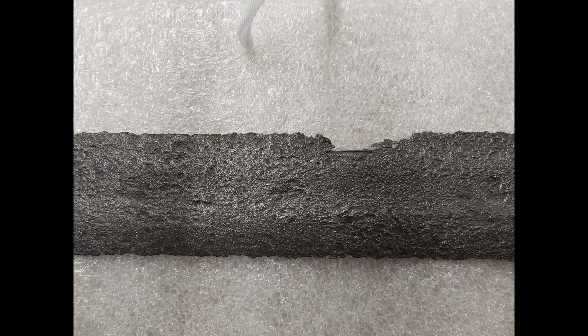We also investigated if the different areas of the sword, for instance the core or the edge steel, have a different chemical composition or can be traced back to different types of iron. That is not the case. The overall chemical fingerprint of all the different areas of the sword shows a quite similar response, hinting that they all originate from the same mine, but with some very interesting nuances.